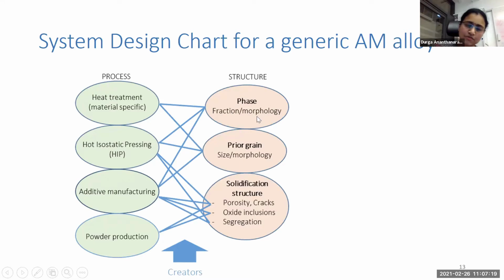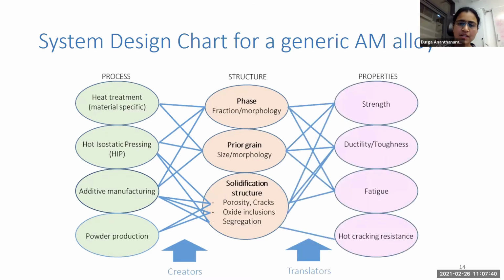And then through each process step, several structural aspects are created or modified. So you will have certain phases forming, transforming. Then the grain structure, for example, is fairly fixed by the additive manufacturing processes. But then you can have recrystallization and so on in later treatments. Then you have several kinds of defects that come up, like porosity, cracks, or inclusions, and segregation in the solidification structure. And all of these then influence different mechanical properties like strength, toughness, fatigue, or the cracking resistance, and so on. So to do an alloy design, really, we have to consider all these aspects.